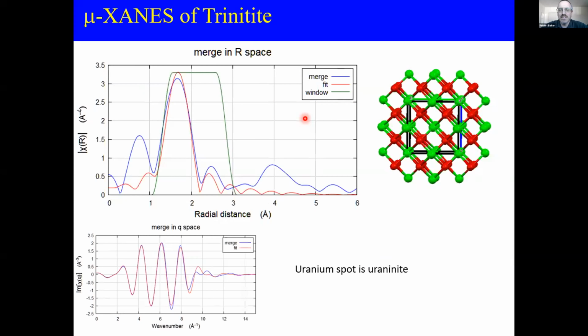And when we look at uranium, it's actually uraninite, uranium-4, which is not really comparable with a highly oxidizing environment that happened in this case. So what we believe happens is that the uranium next to the iron started off as uranium-6 and has been reduced by the iron-2 to form uranium-4, and the iron has been oxidized in the sample to form iron-3.